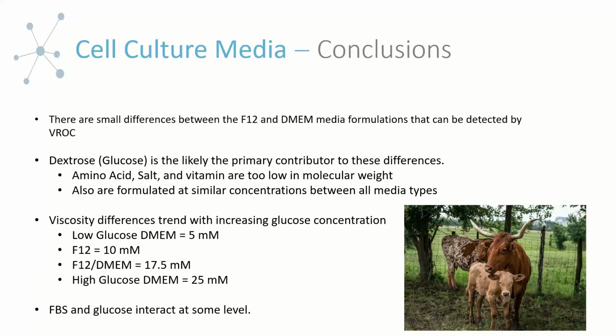So I guess my conclusions are, what was the primary driver of these subtle differences between the F12 and DMEM media formulations that we were able to detect in the VROC? I concluded that dextrose or glucose is the likely primary contributor to these differences. It's a large molecule in comparison to amino acids, salts, and vitamins. And also between the formulations I looked at, the concentrations of amino acids, salts, and vitamins were too similar to really attribute these differences to those specific nutrients. However, the differences in viscosity really strongly correlated with the increasing glucose concentration between low glucose DMEM and F12 and the mixture and the high glucose DMEM. And then also at some level, FBS and glucose interact is the basic conclusion that I got from these experiments that I ran.